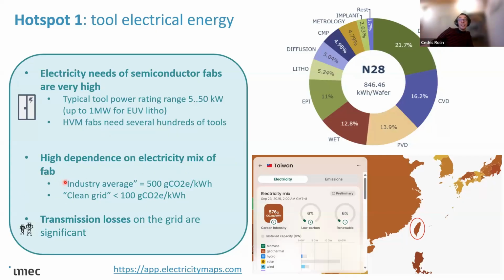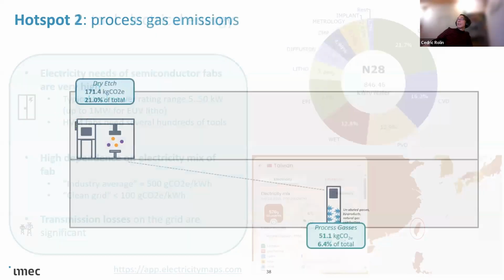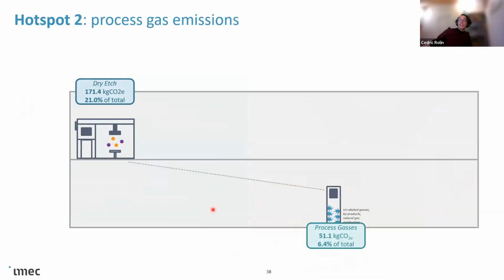We calculated that on average, let's say, semiconductor producing countries have a carbon intensity in the range of 500 grams CO2 equivalent per kilowatt hour, whereas the clean grids would be below 100 grams CO2 equivalent per kilowatt hour. And actually, this picture is also showing the case of Taiwan, where the electricity is actually not very decarbonated in that case. A second hotspot would be related to process gas emissions.